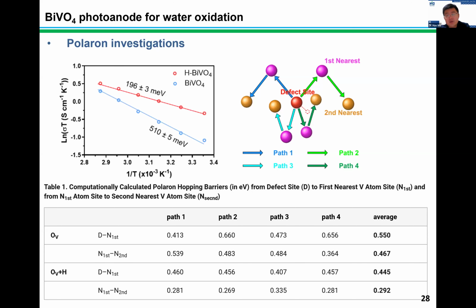And with the experimental and theoretical studies, we again suggest that upon the hydrogen treatment, which sits around the oxygen vacancy of bismuth vanadate, it promotes polaron hopping from the defects to the first vanadium, but more importantly, it promotes the polaron hopping from the first vanadium site close to the defect to the second. So that's why it improved the charge carrier transport, in particular the electron transport, within the bismuth vanadate.